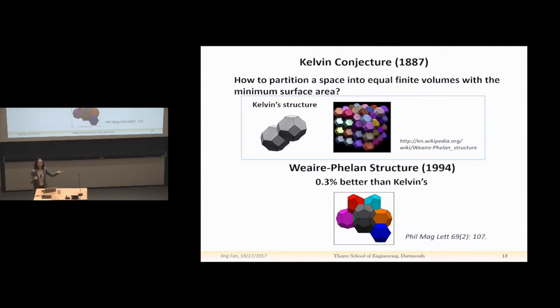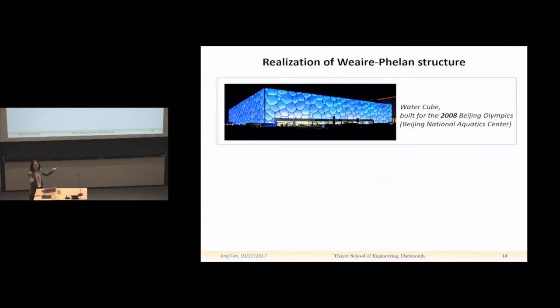Surprisingly, even though people found that the Weaire-Phelan structure is supposed to be better than Kelvin's, in real experiments, in real foam or emulsion systems, people have never observed this structure, although it has less interfacial energy. And why is that?